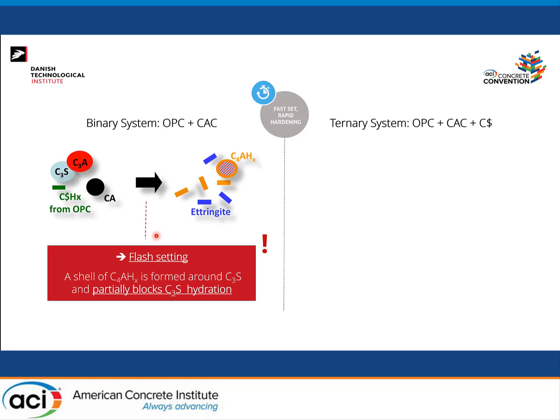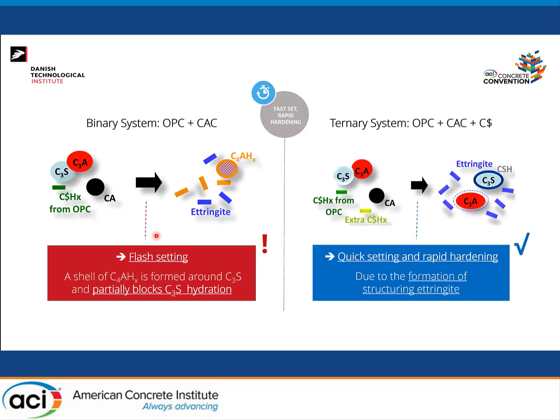So if you provide enough calcium sulfate into the system that you prevent the flash setting effect, then the surplus of calcium sulfate will enable both the formation of the structuring ettringite in the system, plus guarantee that C3S can hydrate as it should. So we are not poisoning the system. That means we guarantee there's a fast setting together with a proper or rapid hardening of the material.